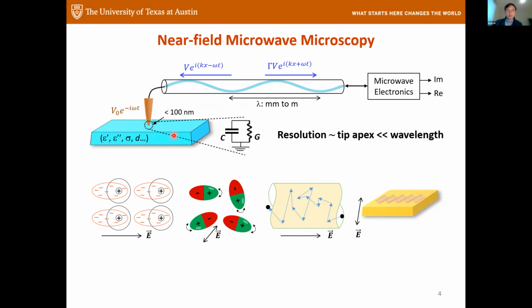Okay. So let me quickly show you a number of MIM, microwave impedance microscopy results on different types of mechanism. This one is on permittivity. The material is Bi2SeO5. It's a fairly good high-K dielectric. And by just imaging this, we can directly read out the permittivity. Of course, we did some simulation, but no need to do any patterning, no need to make a parallel plate capacitor, and we can directly measure the permittivity as a function of thickness.